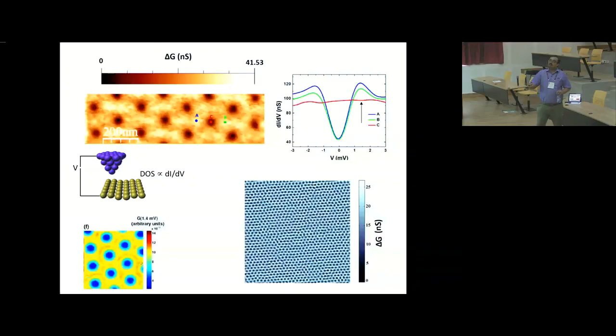So now what you do is you stay at this voltage and keep scanning your tip on the surface and measure the tunneling conductance. So you will get a high tunneling conductance because of this coherence peak whenever you are away from the vortex core, and when you are in the vortex core, you will get a low tunneling conductance. So if you map this, you can get beautiful images like this. This is a high resolution image, this is a large area image. And you can see the Abrikosov lattice in a superconductor.